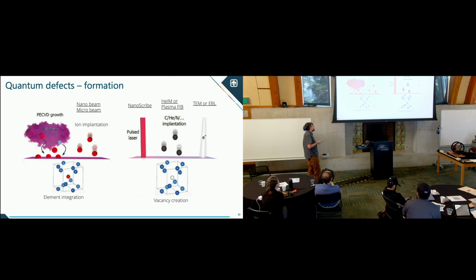And you can actually do it with electron beams, as long as it's 150 keV or more, with TEM or e-beam lithography. Also, a fun thing: Sandia's MESA recently got a fancy new e-beam tool that's 150 keV, more energy than the previous one, but it's perfect for actually making NVs in diamond. So it's just the threshold. And so we're going to take that tool and start locally making NVs with e-beam lithography resolution inside diamond.